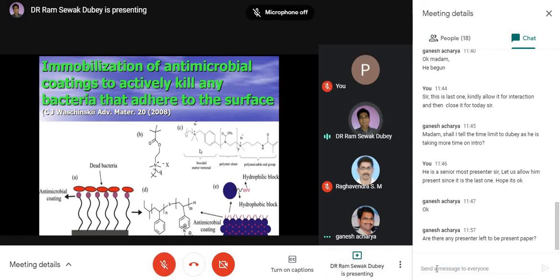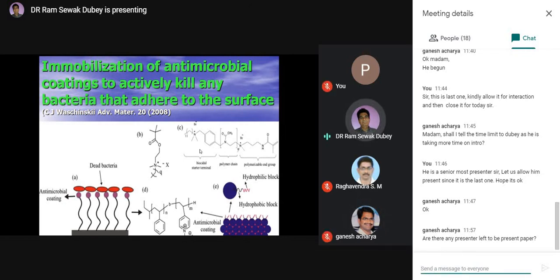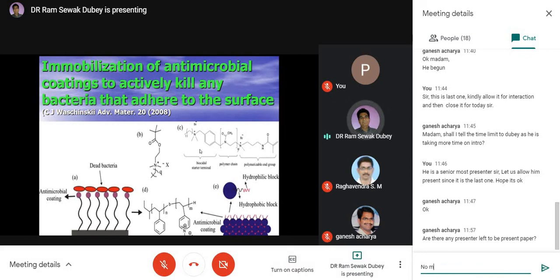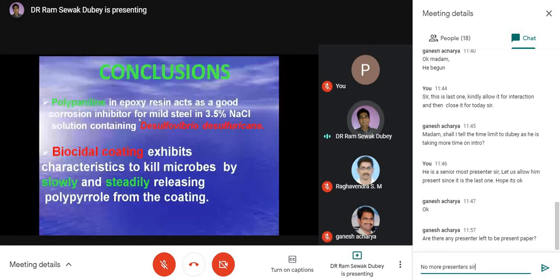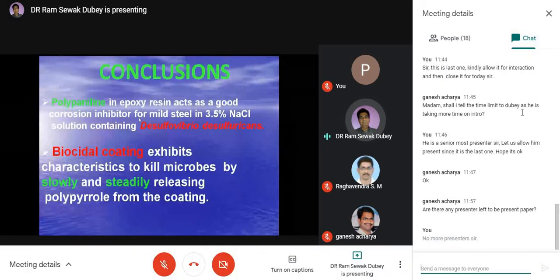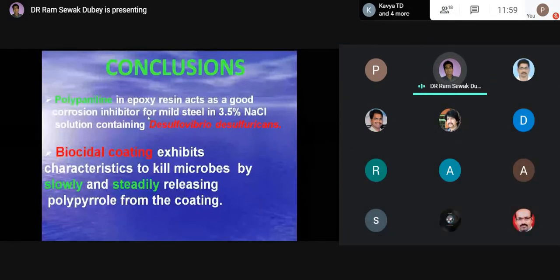How we can say there is a killing of the microbes. Finally, we can conclude polyaniline in epoxy resin acts as a good corrosion inhibitor for mild steel in 3.5% sodium chloride solution containing Desulfovibrio desulfuricans. The biocidal coating exhibits characteristics to kill microbes by slowly and steadily releasing polypyrrole from the surface of the coating.